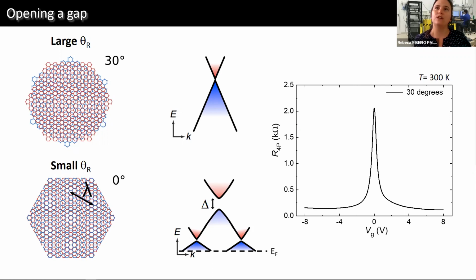There's a question that says, what is the pattern of graphene and BN at 0 degrees rotation between the layers? As they are different lattices, do they not fully overlap like two layers of graphene? So yes, they have a difference of 1.7%. In fact, when graphene and BN are fully aligned, you see this moire pattern.